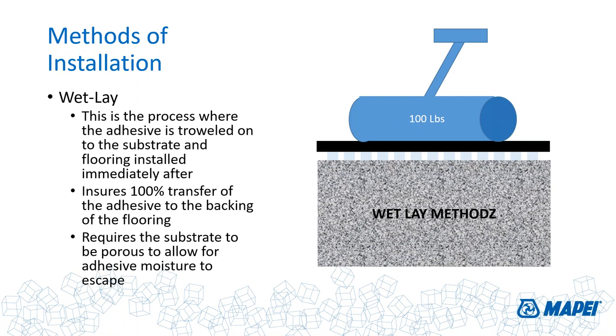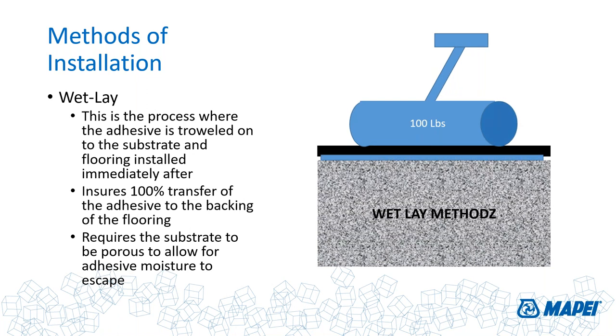Now, a wet lay, which everybody shrinks and dreads about using, is the process where the adhesive is troweled on the floor and immediately installed. The flooring is immediately installed after it. And once that happens, when you hit it with the 100-pound roller, you mash the adhesive down into a complete monolithic layer, and you've got 100% transfer to the back of the flooring, 100% transfer to the back of the substrate, and this is where you get the maximum amount of bonding sites, attachment points. Again, these products in a wet lay method, particularly for water-based pressure-sensitive adhesives, are going to give you the best performance in terms of shear strength. But again, remember, they're thermoplastic adhesives. As long as you keep the temperature change under control, this is going to give you really good performance attributes.